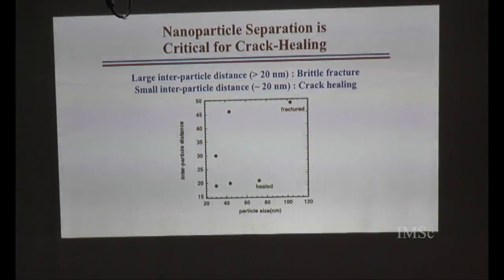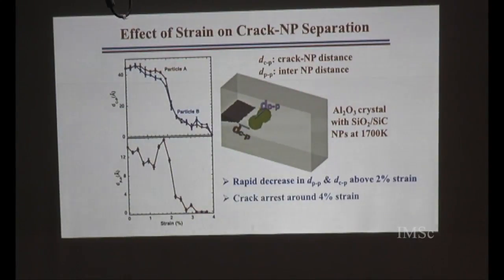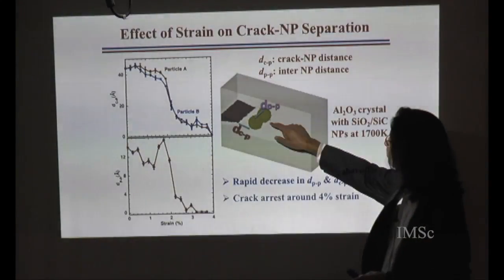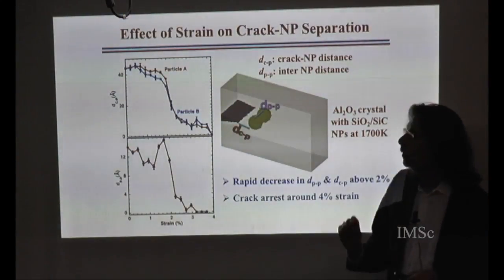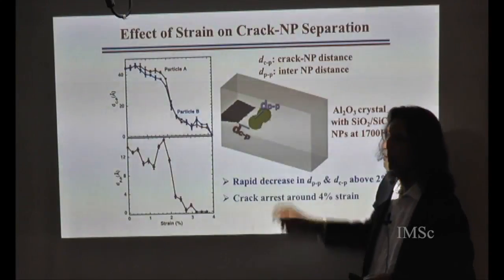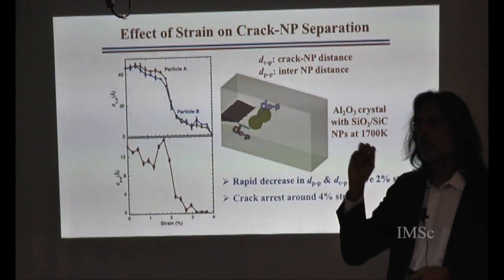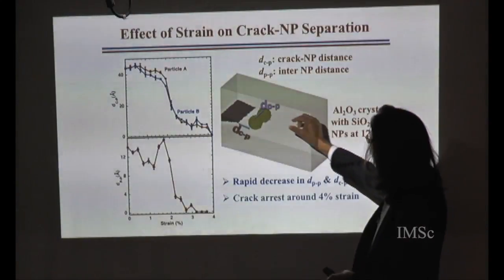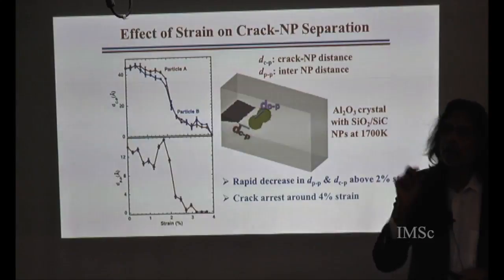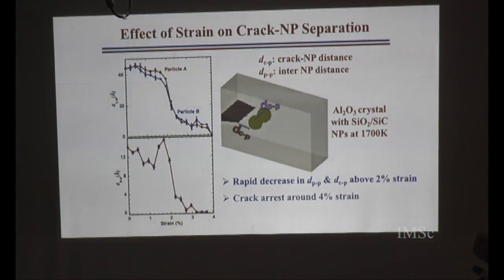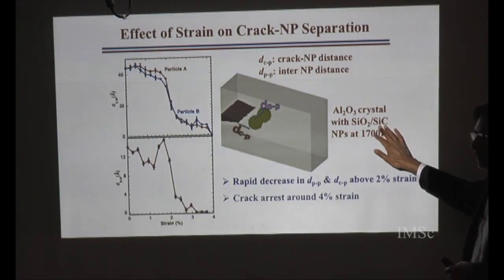So the question is, what is the mechanism? We examined several things. One thing we looked at is the crack to nanoparticle distance, and we wanted to see the effect of strain on this separation. We also looked at the distance between nanoparticles and how that is affected by strain in the system. We are applying strain from outside, and these simulations were done at 1700 degrees Kelvin because we wanted to be close to the experiment I described, which was done in Japan, in the same ballpark.